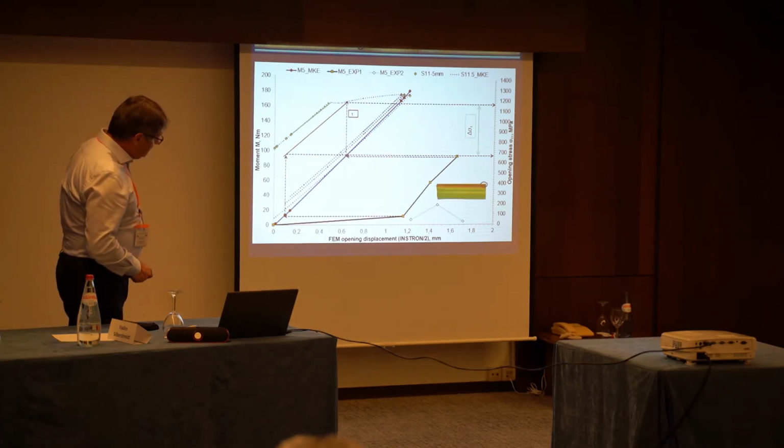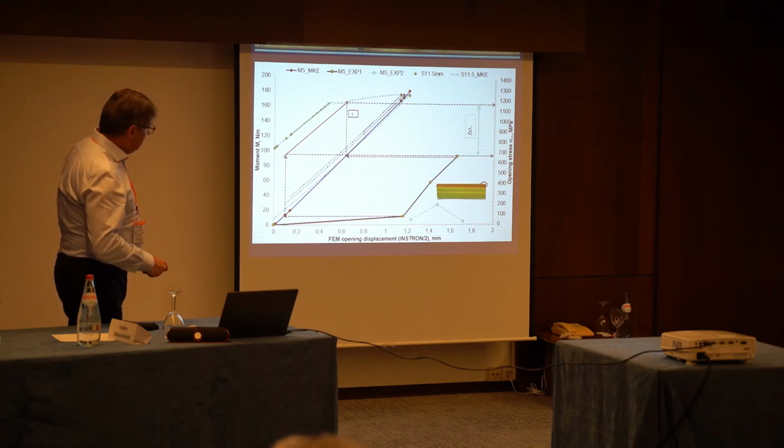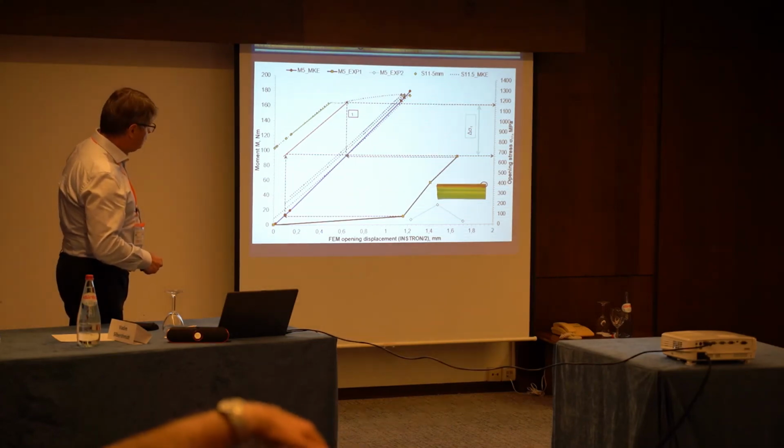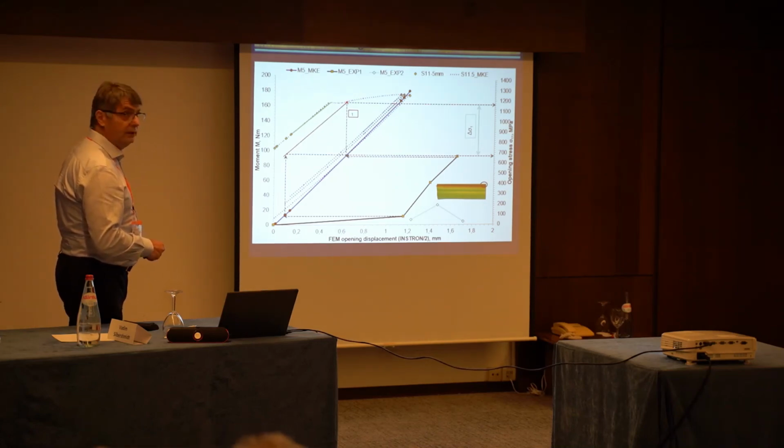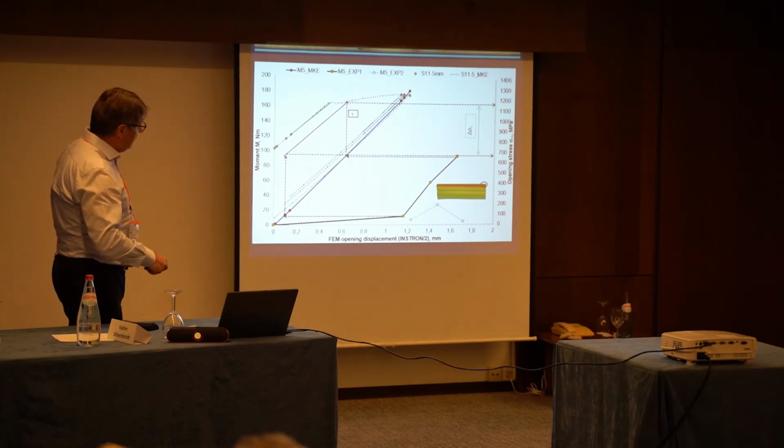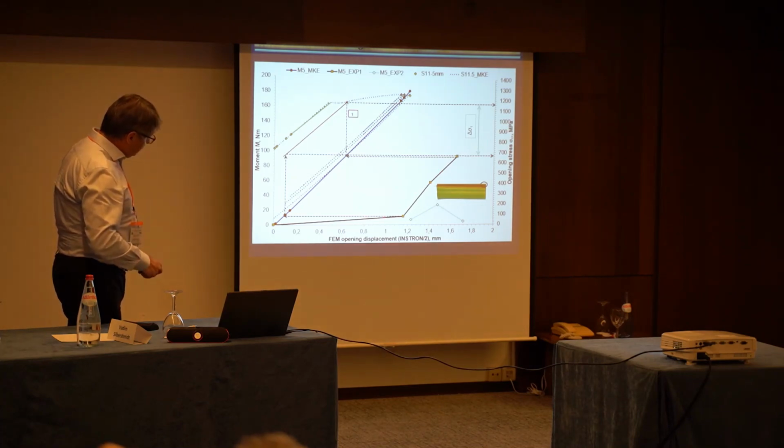And what we did here was to make the linear line, and if you know that this linear is maximum, you come onto this loading path from the finite element computation, and you get the value of your stress at this point. Then when you do the unloading with this curve, which should be similar to this one, you come from this point, which corresponds to your ratio of loading.